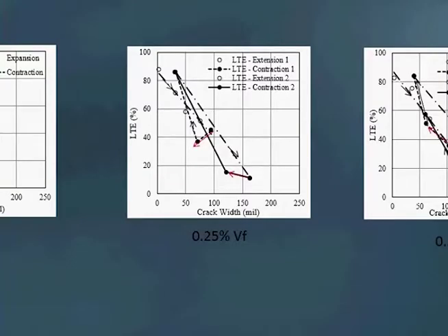One more important thing we noticed here is this: synthetic fibers are good, but there is something called stress relaxation. If the crack width increases, fibers get some plastic deformation. So conversely, when the crack width becomes narrow, the fiber doesn't contribute if it is not stressed. So that's something we should also be looking at. Here you see, this was plain concrete. Basically, we widened the crack width and then pushed back. When we push back, we saw something similar, but in terms of the fiber, when you push back the crack width, the load transfer drops.